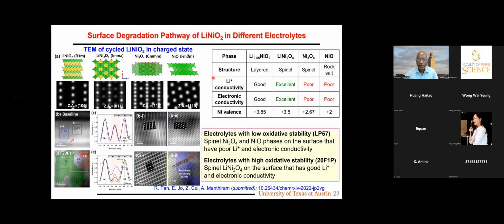So why does the other material cycle well? Another reason: I've listed 4 materials here. This is the original. Sorry, there is a typo here. It is Li 0.85, not 0.15. That's a layered structure. During the surface reaction, this material forms LiNi2O4 in the case of good electrolyte. Both of the 2 good electrolytes I showed, LSC as well as FEC with LiPO2F2, form mostly only LiNi2O4 on the surface.